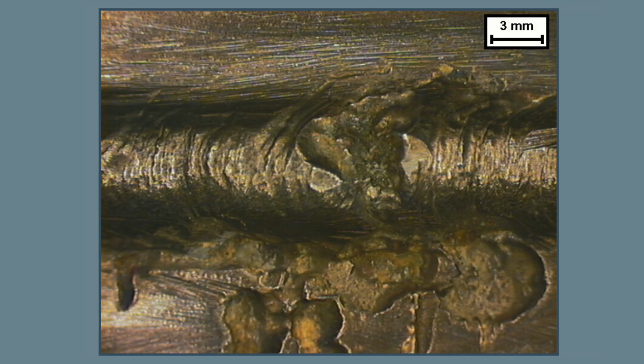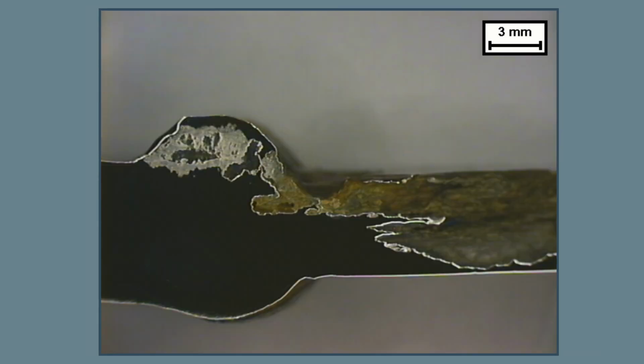It took us quite a bit of time to figure out that it was actually under deposit corrosion, because the samples we removed, this is of the corrosion attack, and you can see there's not much deposit on the sample that we received from the customer. So we did an investigation. I think the next image shows a cross-section through that pitting corrosion, where we can see massive subsurface corrosion or attack into the steel, resulting in leaking. From this investigation, like I mentioned before, it was a BIOX reactor, so it was a very corrosive environment. And we looked at it, we couldn't understand why it was pitting. So we looked, and the weld was fine.